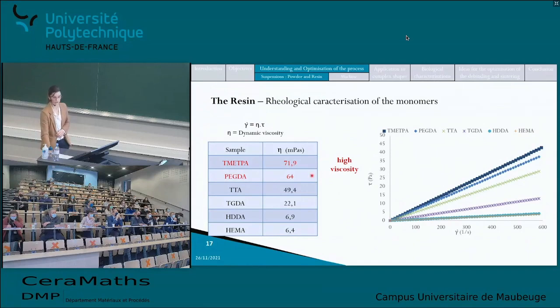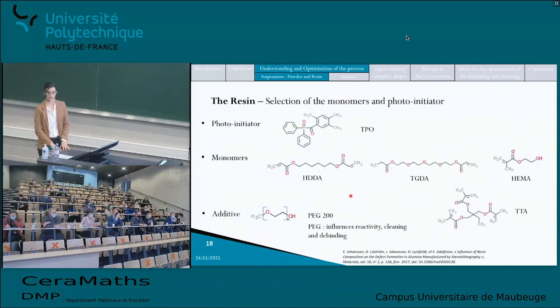and one photoinitiator that worked, the TPO. I also realized that in most of the composition of the resin that are presented in the literature, the acrylate monomers are not used on their own. They're often used with an additive that can improve the reactivity, the cleaning, and the debinding step. So I selected the polyethylene glycol 200 for this purpose.